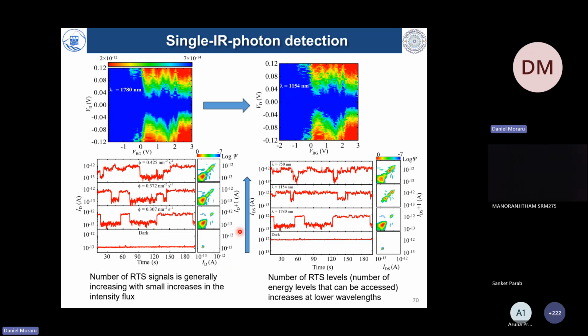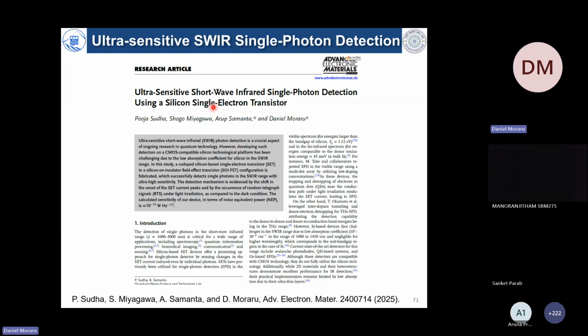as the flux is actually increased. Even if we irradiate with 1154 nanometers, we can still see this multiple level RTS, and now we can compare it with other structures. In this case, this is the wavelength effect, and on the right is the photon flux effect. So we finally understood that we can actually detect photons not only in the visible range, but also in near and far infrared regimes, and that demonstrates, as shown in this paper, ultra-sensitive shortwave infrared single photon detection.